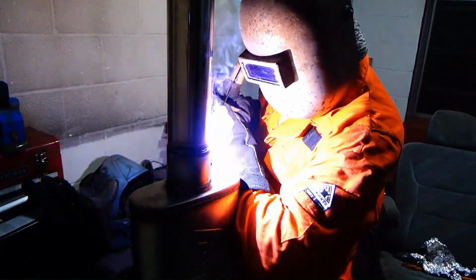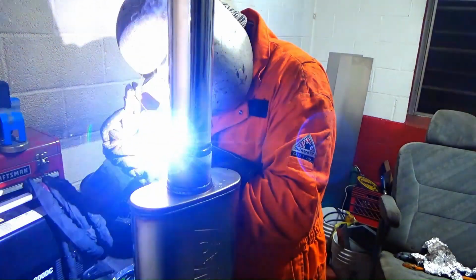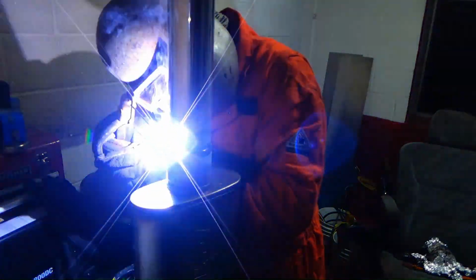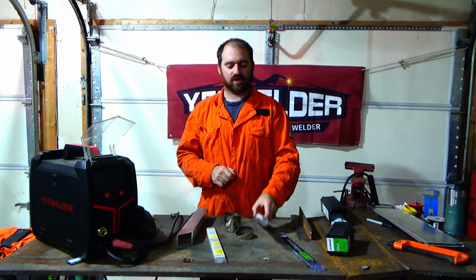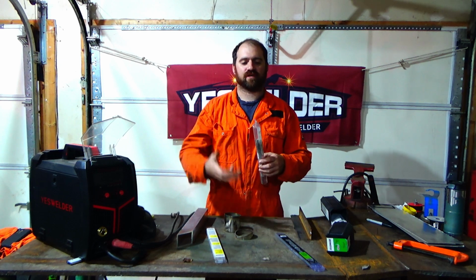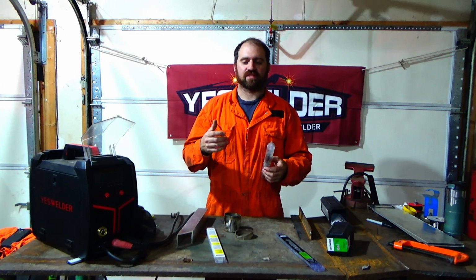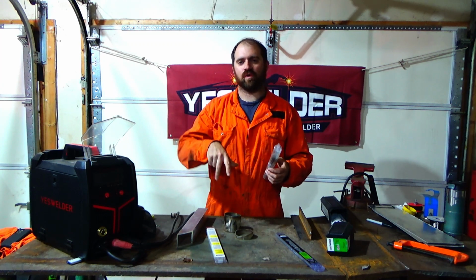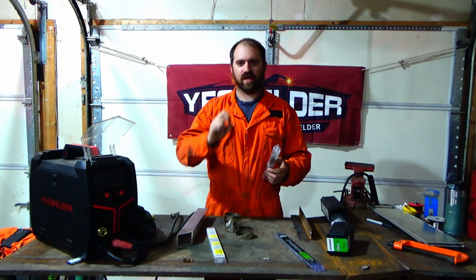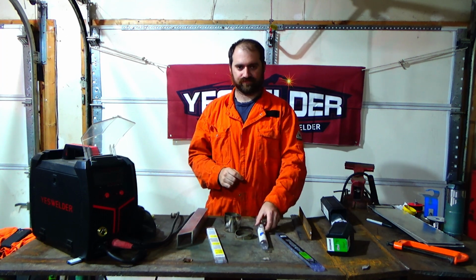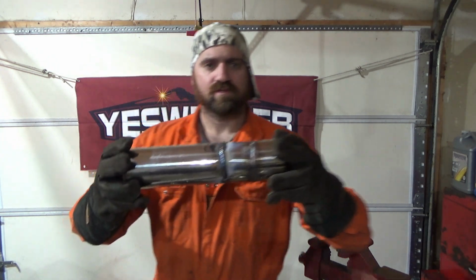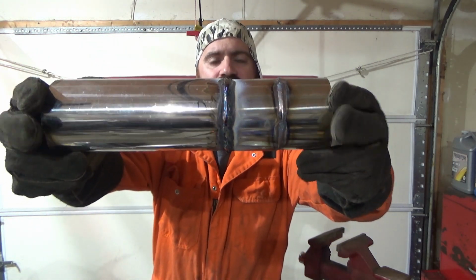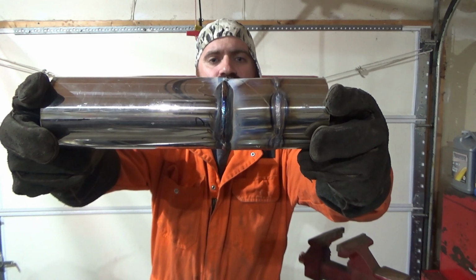So this is not a weld that is very easy to do because of how thin the tubing is and how thin the rods are. And these rods also create a very thick layer of slag that can be intrusive to the weld. If you get ahead of yourself a little bit, that slag will carry ahead of you, get under the weld, and leave nice slag pockets. Not a fun thing. And these slag pockets, there is no burning them out. So that's welding stainless steel with stick welding electrodes.